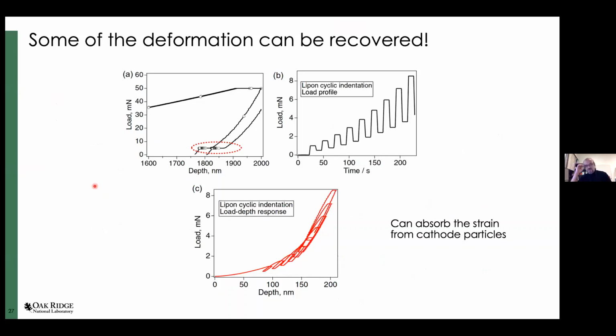Now, the weirdness doesn't stop there with LiPON. So this is a part of the load-depth curve from the nanoindentation, and this is the part of the unloading segment. And typically in routine practice, what we do after unloading is hold it at 1/10 of the peak load. So if the peak load was 50 millinewtons, you unload and hold it at 5 millinewtons, just to estimate if there is any thermal drift in your experiment. Now, being very careful, we measure thermal drift before the experiment as well on fused silica, and it should be less than 0.1 nanometer per second. If you look at this displacement here, it's much larger than that.